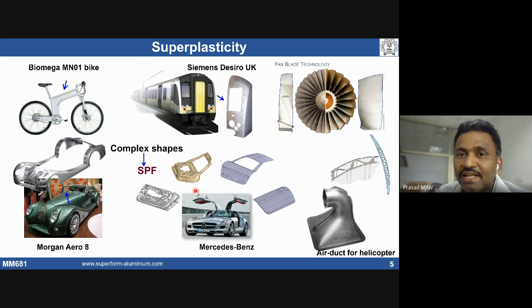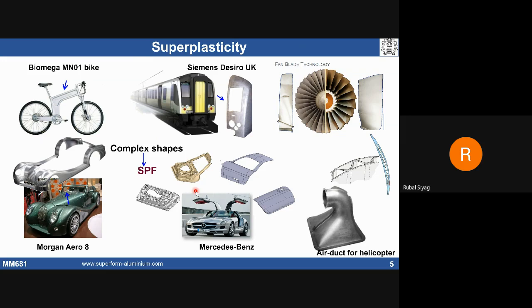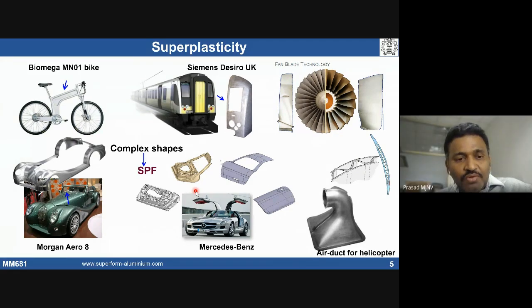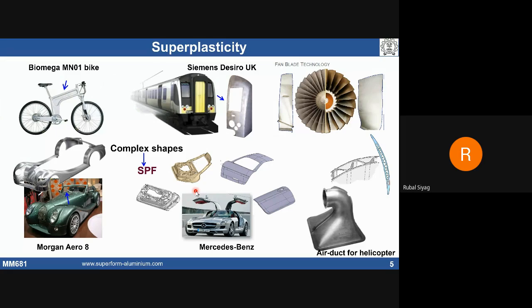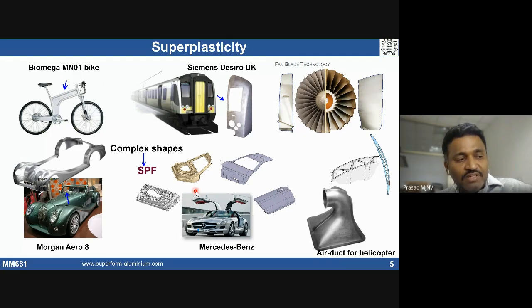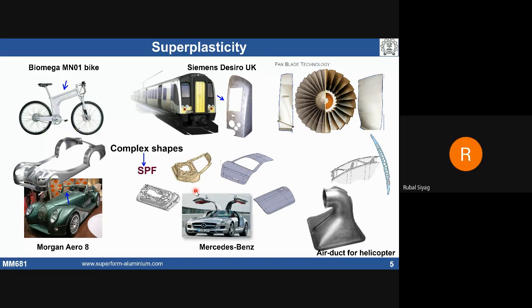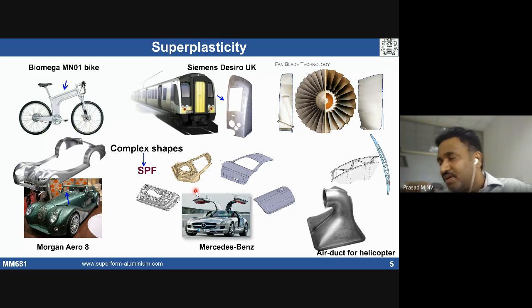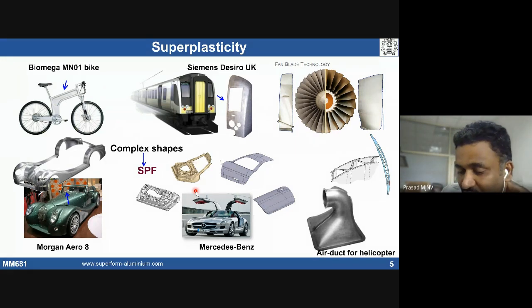What are the requirements for a material to exhibit superplasticity? Fine grains, low strain rate, high temperature. Anything else? It should be free from cavities or defects. I think you listed almost all of them. Basically, superplasticity is considered an elevated temperature phenomenon. If we have a high temperature, diffusional activities are going to be higher.